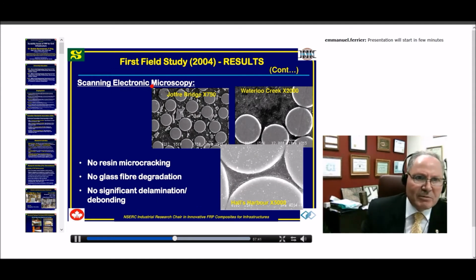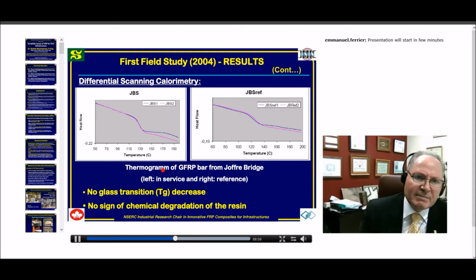Also, this is about scanning electron microscopy. Here I'm showing some slides, but we did hundreds and hundreds of specimens, and thousands of pictures, and looking at them, we did not see any resin microcracking, no glass fiber degradation, or any significant delamination in this material.